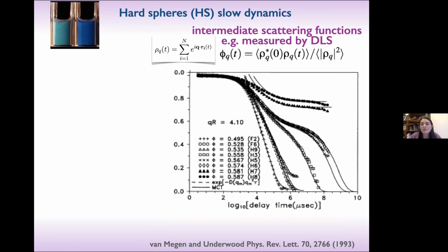For now, let's concentrate on the symbols, which are the experimental measurements. We will go back to the lines later. At low packing fraction, you see that there is a single relaxation. Then as you increase further and further the packing fraction and you approach the glass transition, there is a second decay. And if you further increase the packing fraction above 58%, the system becomes arrested, and on the time scale of these measurements, the system arrests.